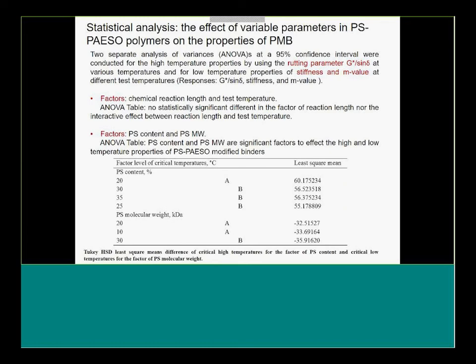So this is where we get into looking at some of the statistics, and we're verifying that there's a statistical difference between 20% polystyrene content versus 30, 35, and 25. What this is telling us is, in fact, we get enhanced high-temperature grade improvement using lower polystyrene content. In asphalt we're typically using 30 to 35% polystyrene, so we're paying more for our polymers that isn't enhancing the performance of the asphalt.